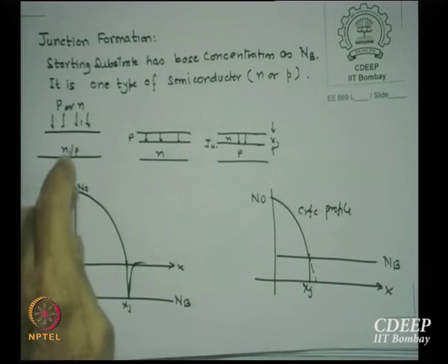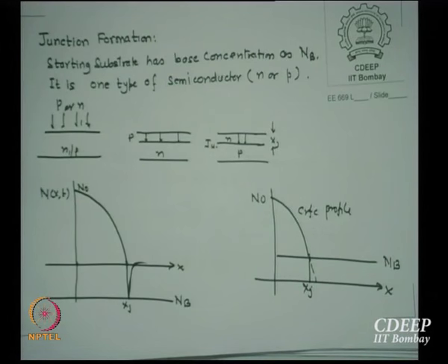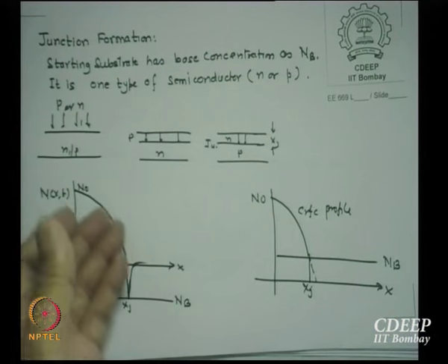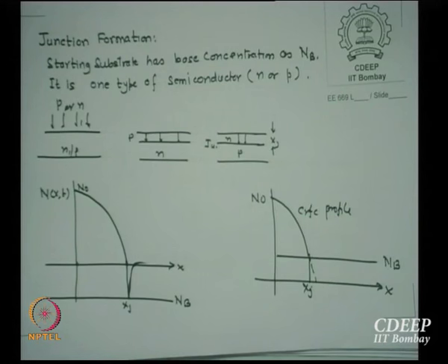As the impurities start from the surface, their concentration starts reducing. Let us say the background concentration was some number smaller than the surface concentration we start with. As this concentration decreases, at a certain point the net acceptor impurities are equal to the net donor impurities. Assuming all are ionized, which may or may not be true every time, electron and hole concentrations are equal, or they neutralize and recombine. It's called compensation. A p-type impurity will compensate the n-type impurity, and when that compensation becomes zero, with concentration equal on both sides, we call that a junction.